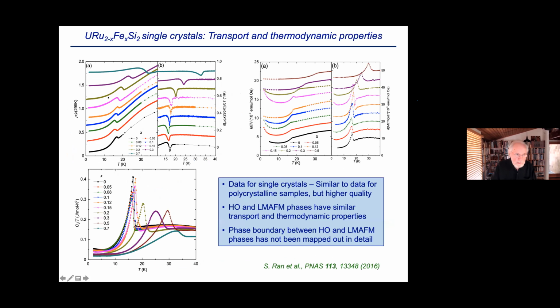This just shows you the measurements upon which we base this phase diagram. This is normalized resistivity versus temperature, and you see features due to the hidden order transition down in here, and the antiferromagnetic transition up here. These are just derivatives to accentuate the features. You see similar things in the magnetization, in the susceptibility, if you like. And this is just another way of representing the data, where you can make these features look more like the specific heat by taking this kind of a derivative. Anyway, you can see the transitions in all of these features.